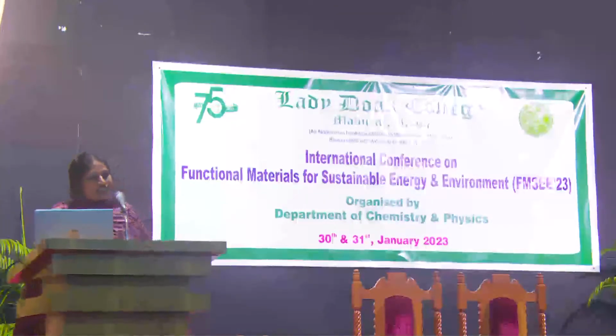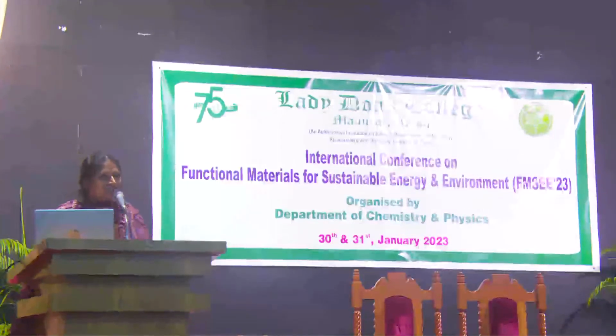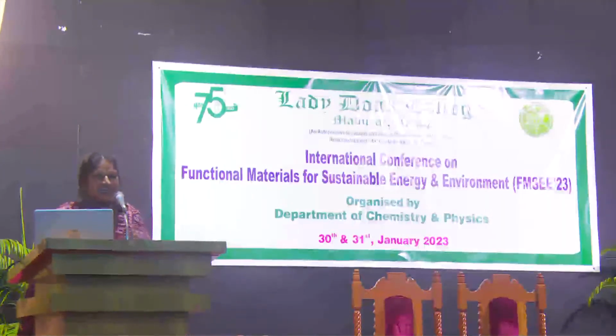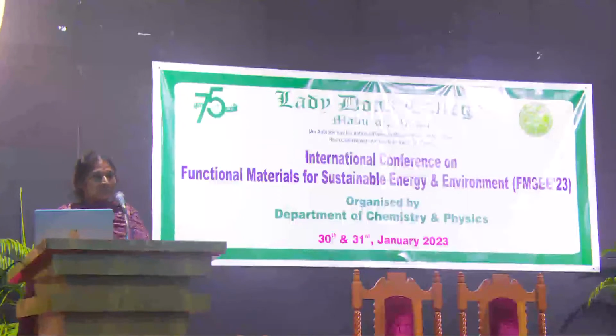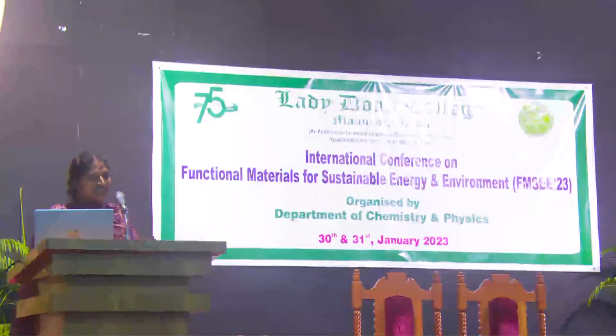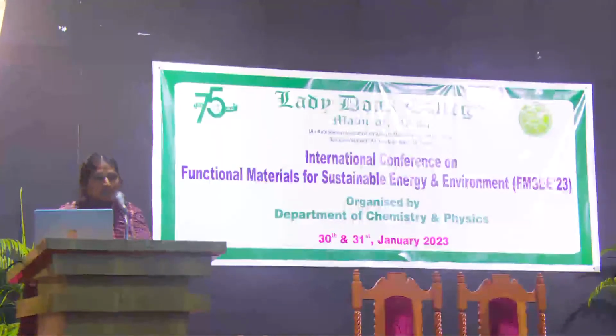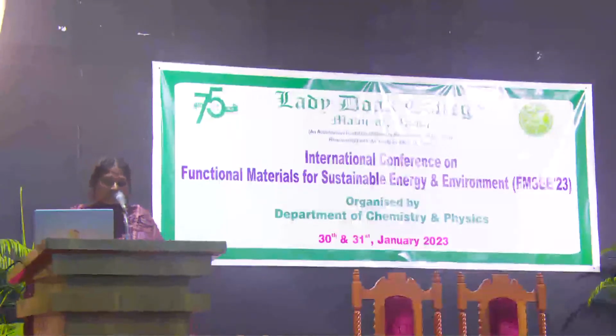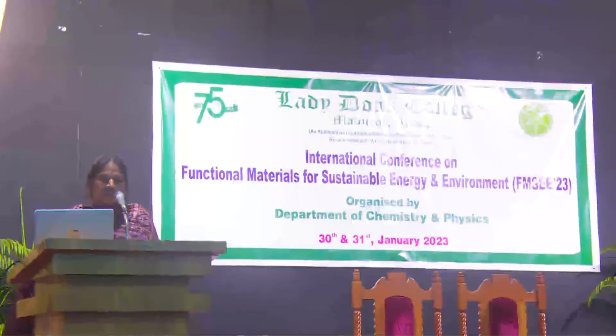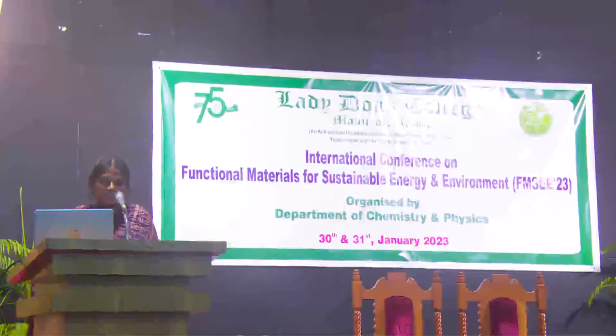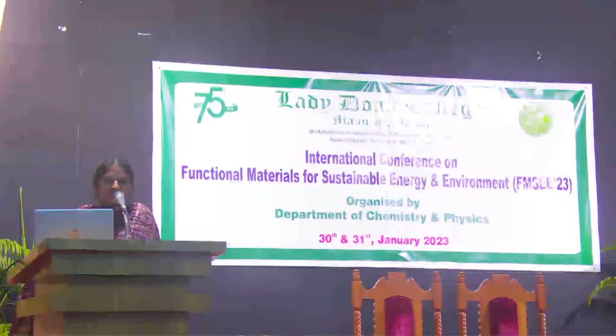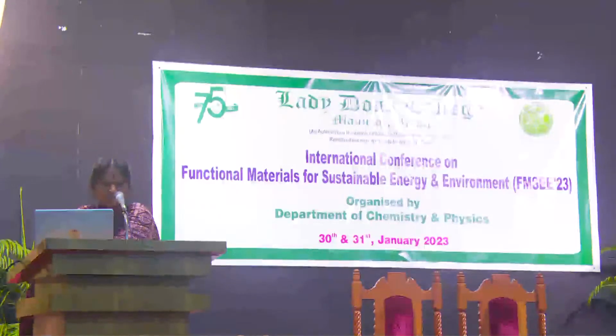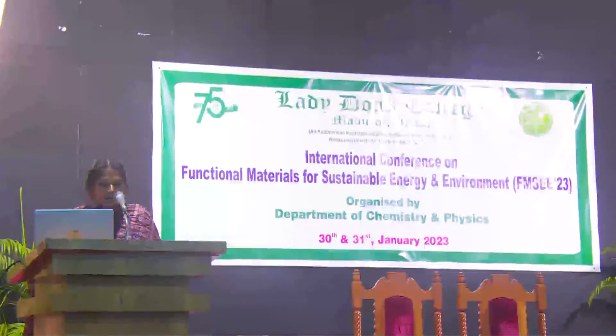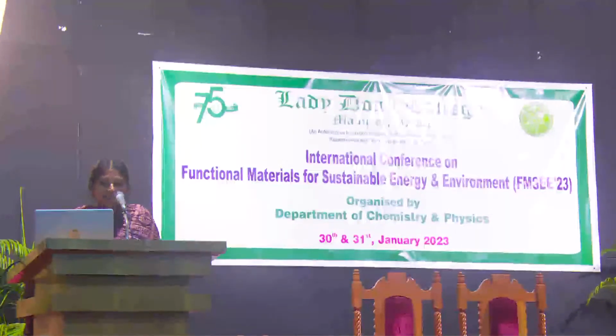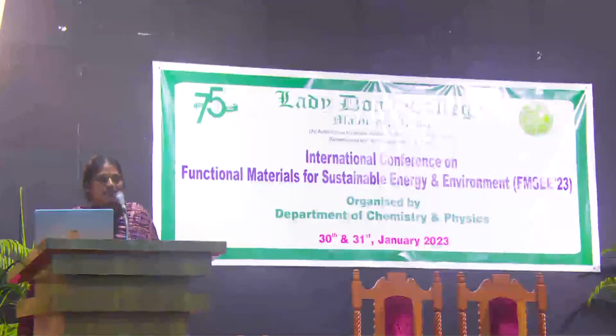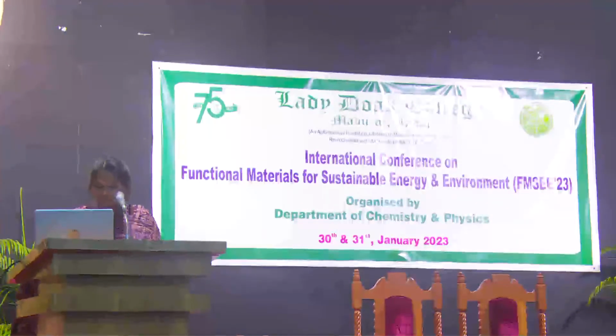And this is the synthesis part of my material. It's a direct one-step chemical activation method. As usual, the seed is collected, washed several times, dried under direct sunlight, then finely chopped and powdered. Once it is ground, this image was taken. There are no pores noted. It's like dry sand. After activation with KOH and high temperature pyrolysis, we can see hierarchical dense pores. So activation and pyrolysis play a major role in pore formation.